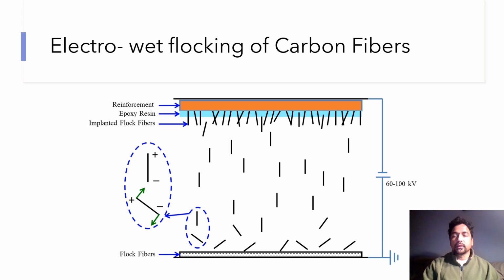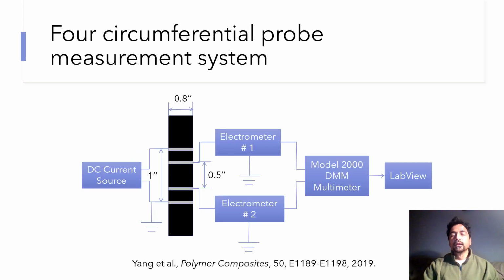This way we reinforce short carbon fibers, and once we make these short carbon fiber reinforced fabrics, we stack them up and then apply a vacuum infusion process to make the composite, in addition to compression molding. Once the composite sheets are available to us, we cut them into rectangular strips, where we use a four-point probe measurement technique to measure the resistance of the composite. In this presentation, we wanted to understand how the various parameters we control in the flocking process affect the electrical resistivity of the composite.